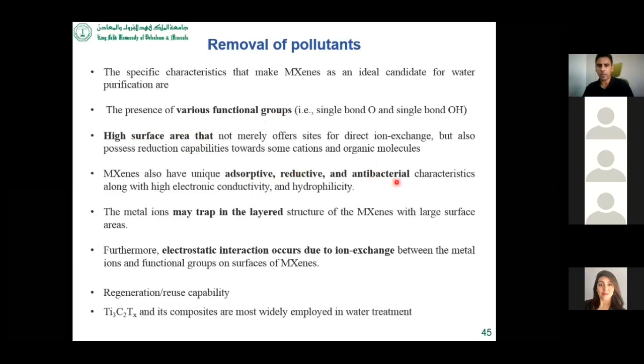It has some antibacterial characteristics, okay, and the molecule can be trapped into the layers, because there are various layers, so it can be trapped between the sheets, so it can be removed. Then if you modify the surface, of course there will be electrostatic interaction due to ion exchange, in addition to the adsorption. So all these are very attractive features, and most interestingly, you can regenerate these materials, so they can be employed in multiple cycles, okay, which is the requirement on commercial scale. This is one of the attractive features.